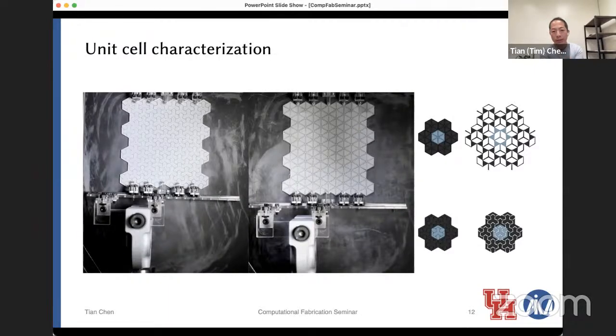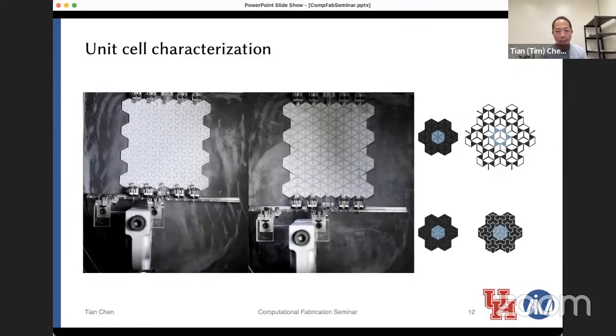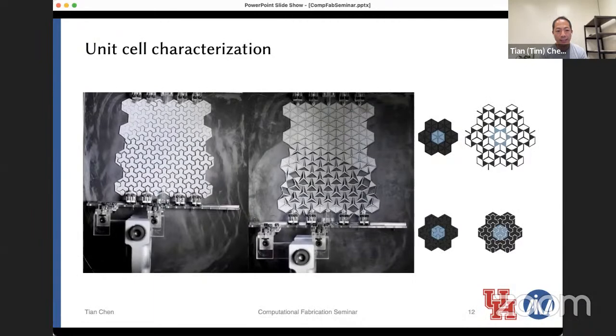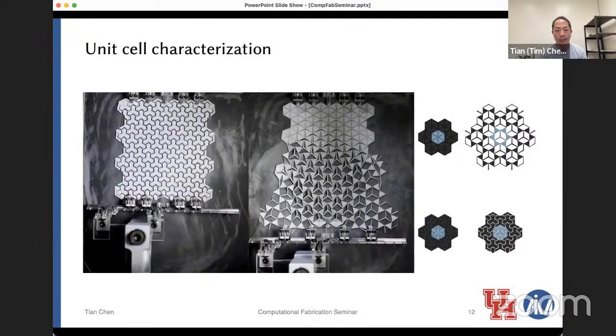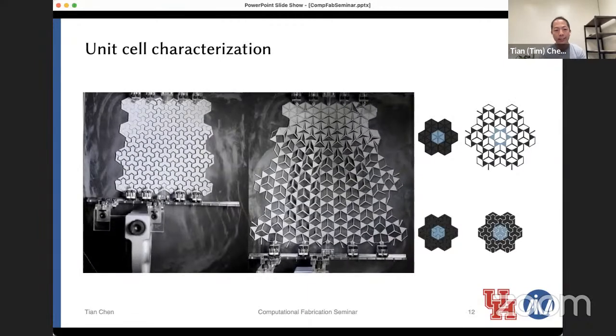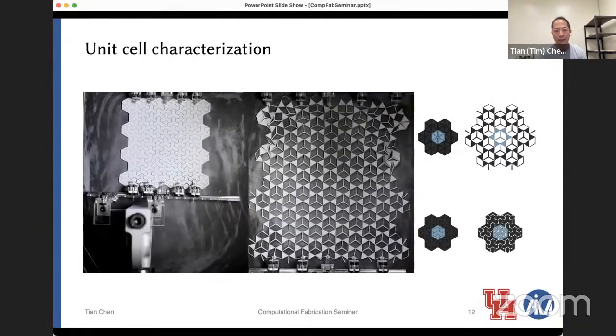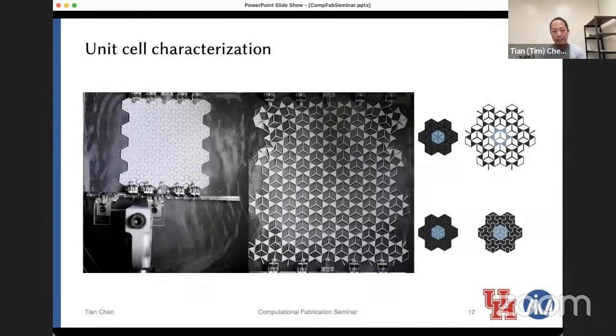And we turn to mechanics to answer which unit cell we should pick to get the expansion ratio we want. To study the mechanics of these unit cells, we first tried to do an experiment. Building this very complex experimental setup that replicates this periodic boundary condition, we're able to mechanically test the expansion behavior. This was quite successful in terms of getting the final state, but it's not very successful in getting the intermediate forces because each unit cell snaps at a different time. So when you look at the force displacement curve, it's a mess until the very end. This is not exactly what we need because we need to know the behavior of each individual unit cell at all stages of the strain.